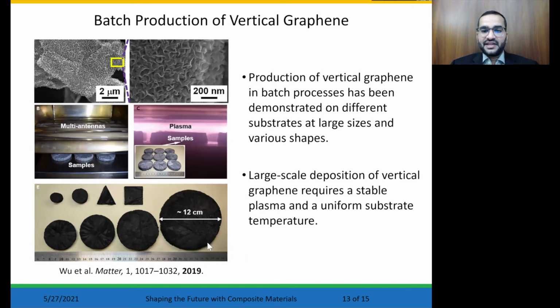They showed that vertical graphene can be deposited in large scale with different sizes. The main parameter to have high quality graphene at large area is to have a stable plasma and have a uniform substrate temperature, which can be heated by the plasma or supplementally using a heater.